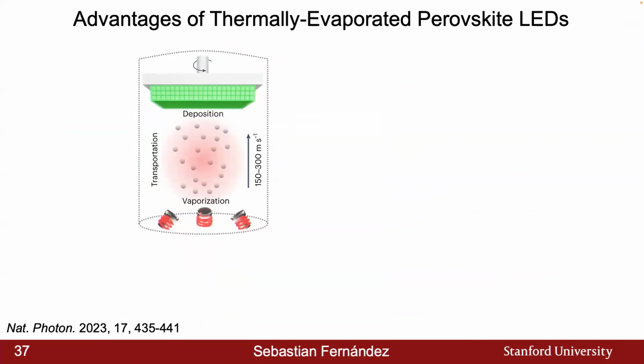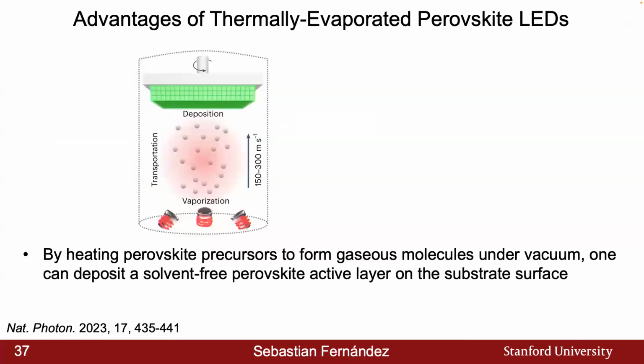So how this works is we can load those same perovskite precursors into this crucible, pump the chamber down under vacuum, and evaporate them by applying a lot of heat within the crucibles. These gaseous molecules will interact within the chamber, leaving behind a solvent-free perovskite active layer.